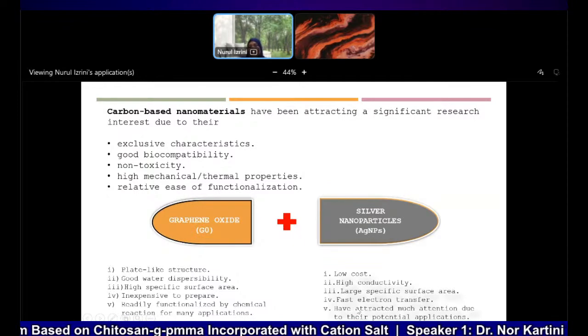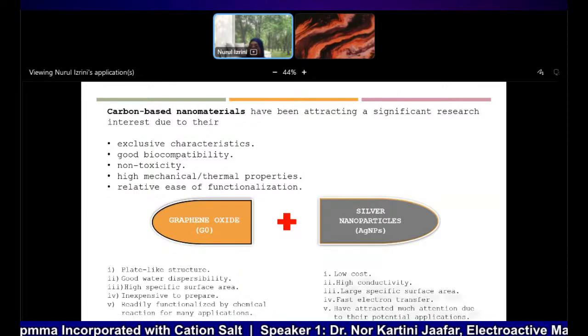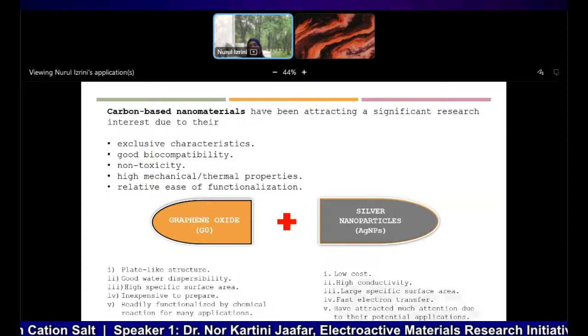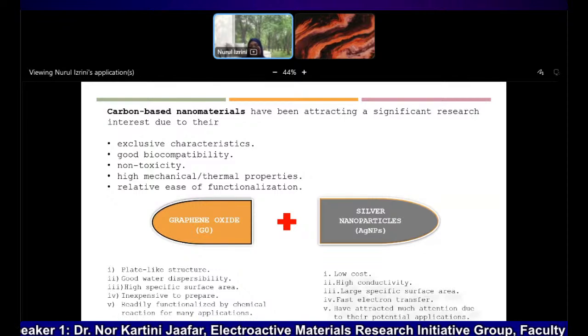However, silver nanoparticles have limitations because silver is not stable, easily corrodes, and easily agglomerates. So when we hybridize with graphene oxide, the graphene oxide can anchor or give support in order to avoid agglomeration and make the silver nanoparticles more stable.